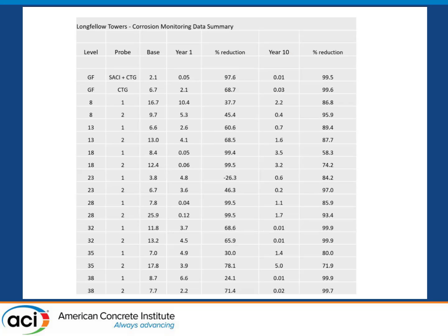But what I think is unique about this job is not just visually, but now we have data that goes along with that. These were the results of the baseline data, prior to the repairs being initiated. In this case, the red are high rates, right? If it's above 10, we've got 16, 25, 11, 13. So some pretty high corrosion activity.